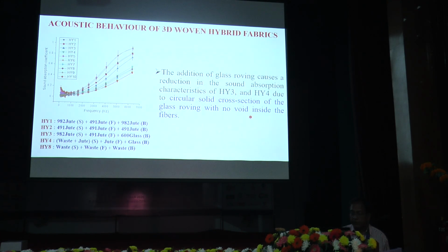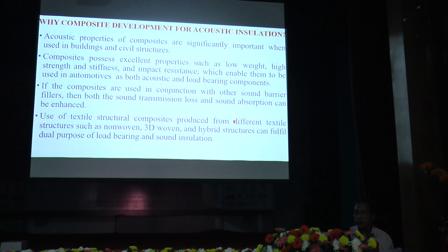Then here we also have the sound absorption coefficient, and you can see that the addition of glass roving has caused a reduction in the sound absorption characteristics of HY3 and HY4, because glass has a solid cross section, and due to this solid cross section, there is no void inside the fiber, so it causes a reduction in the sound absorption coefficient.